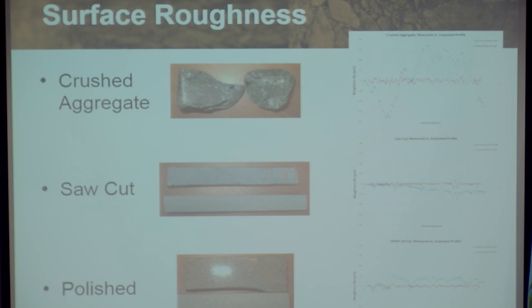And we were very interested to see how much difference there was in terms of the surface roughness or the surface profile. And there are differences. You can see on the right-hand side, the slides haven't come out that well, but there are differences. But to a certain degree, those differences tended to be on quite a large wavelength. So if we were only looking at very, very small changes in the profile, we weren't that dissimilar. So although we weren't obviously trying to replicate exactly what we would find in an aggregate that was used in asphalt mixture, in terms of localized profile or localized roughness, we were fairly happy that if we used a robust sawing process, we could produce these substrates that were very similar in terms of the surface profile of a normal aggregate used in an asphalt mixture.